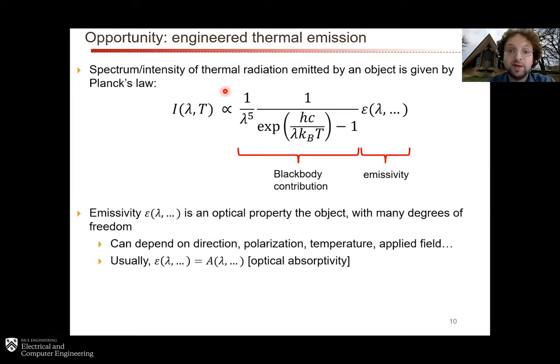So in general, the spectrum of thermal emission is given by this Planck blackbody contribution, which is dependent on wavelength and dependent on temperature and then a bunch of constants, but it's also dependent on the emissivity, which is this parameter that's between 0 and 1 that tells you how likely the object is to emit a photon thermally. So what is the propensity of the object to emit?